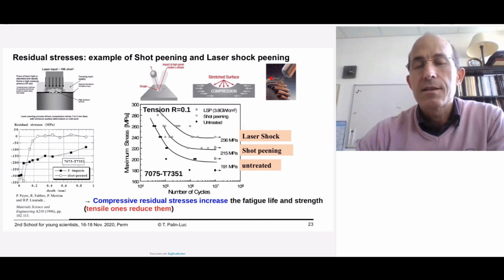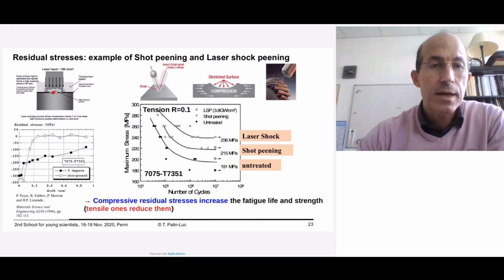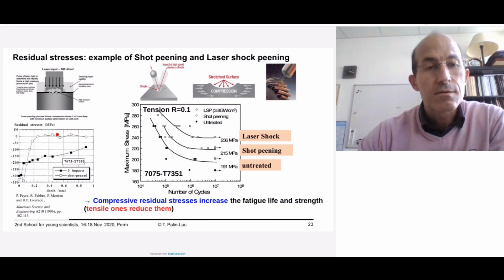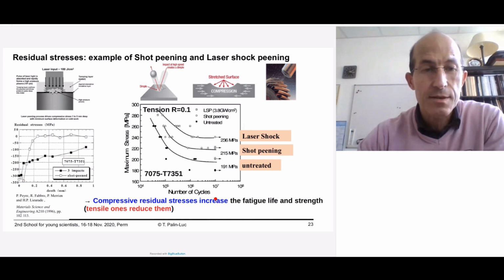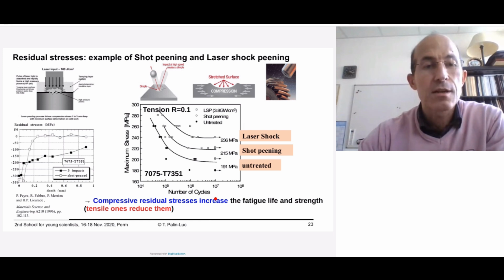Another treatment is the laser shock peening, where there is no ball creating plasticity, but a laser impact which produces a plasma, and the wave due to this plasma creation here will produce plasticity. So the consequence of such surface treatment is that if you look at the residual stresses versus the depth of the material, you obtain such a profile: at the surface a compression state, and in the depth, a peak in tension in order to have the equilibrium. So the peak in compression at the surface is very good for fatigue resistance because the compressive residual stresses are static stress in the material, which are opposed to the tensile opening stress of the cyclic loading. So the compressive residual stresses will increase the fatigue resistance.